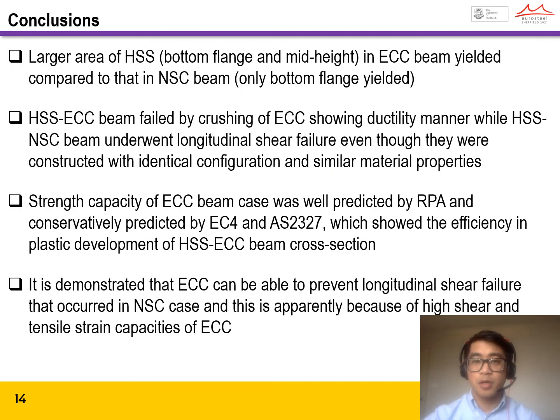Several conclusions can be drawn from this study. A larger area of high-strength steel in the ECC beam yielded compared to that in the NSC beam. The high-strength steel ECC beam failed by crushing of ECC in a ductile manner, while the high-strength steel normal-strength concrete beam underwent longitudinal shear failure, even though they were constructed with identical configuration and similar material properties.